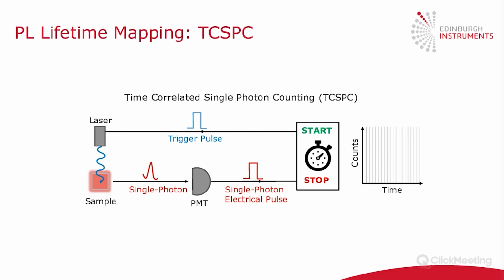For those of you who do photoluminescence microscopy, you're probably very familiar with this. For those of you who come from the Raman side, you might never have heard of TCSPC, so I'll give a brief overview. We can image the photoluminescence lifetime using a technique called time-correlated single photon counting. The idea here is the laser fires and excites the sample. When the laser fires, it sends a trigger pulse to the electronics, which starts a clock. The photon from the sample is emitted and detected by a PMT, and this is converted to an electrical pulse that stops the clock. So you measure the difference between the start and the stop time, and then you build this up in a histogram.